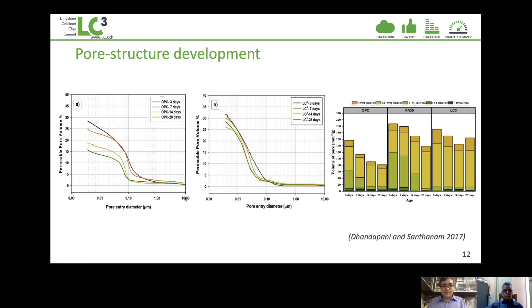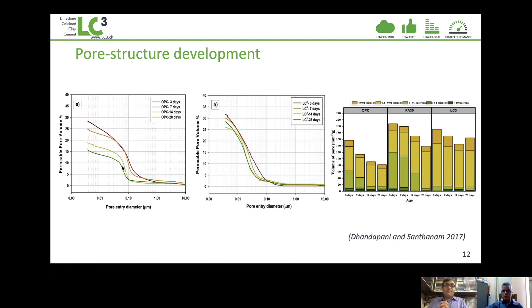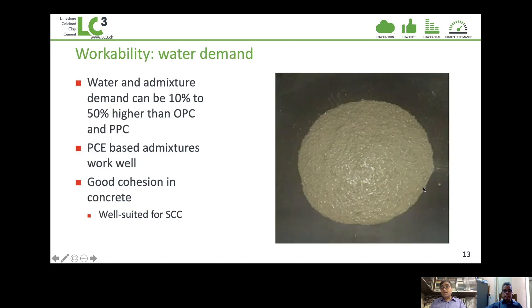An excellent result of this hydration is that LC3 achieves a highly refined microstructure. It reaches a threshold breakthrough diameter within three to seven days that ordinary Portland cement achieves only after 14 to 28 days. Despite shorter curing, LC3 develops a finer, denser microstructure with lower permeability. Although total porosity may be higher, a larger proportion of that porosity is in the finer pores, with the coarser pores being much smaller in volume — which significantly reduces the permeability of concrete.